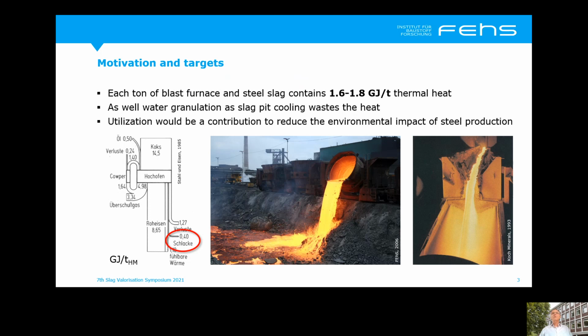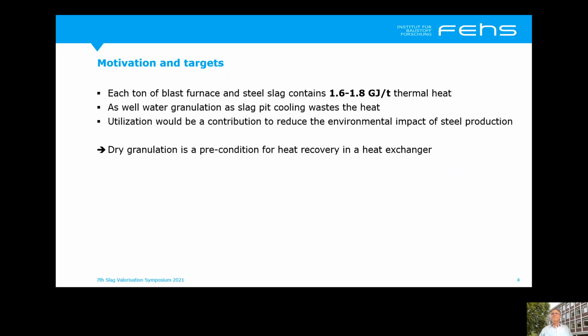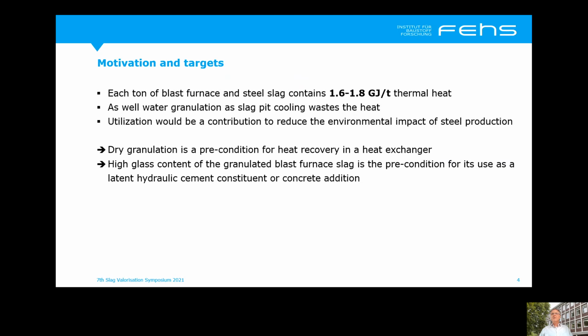However, as well the water granulation for GBS as the slag pit cooling waste the heat. Utilization would be a contribution to reduce the environmental impact of the steel production. Dry granulation is a precondition for heat recovery in a heat exchanger, and the high glass content of the granulated blast furnace slag is a precondition for its use as a latent hydraulic cement constituent or concrete addition.